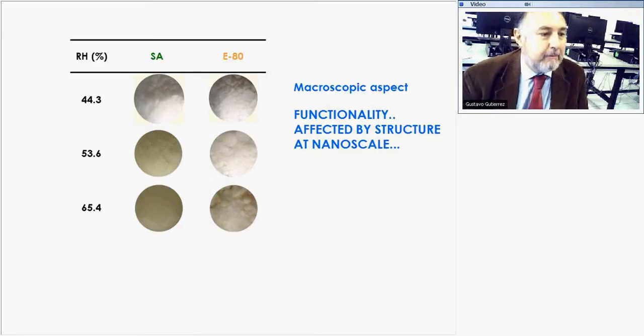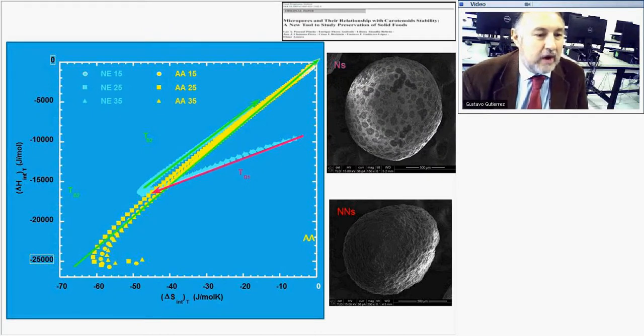You can see both of the materials, as scanning microscope images, and the spray dry at 65.4 relative humidity in the environment collapses, while the material where the ethanol at minus 80 preserves its powder condition. Let's move on to another one.